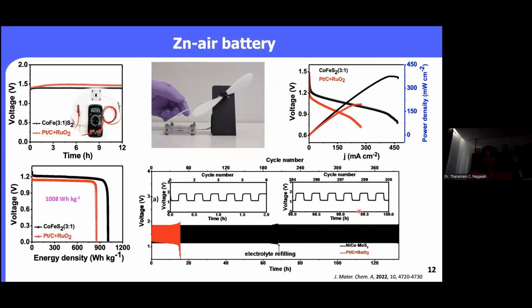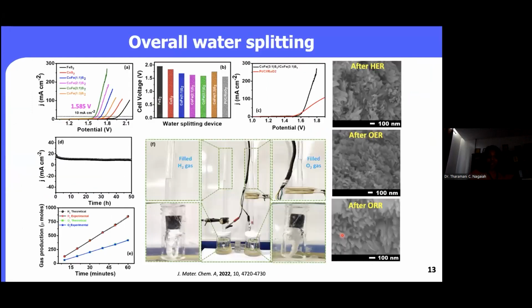And we have done the long-term stability experiments in this case. In the long-term stability test, you can see that the platinum carbon shows almost the decay in the current in less than 20 hours. Whereas in the case of our catalyst, after 70 hours, you can see that there is an increase in the potential gap. And once we refill the electrolyte, it is regained and the potential gap is maintained almost constant even up to 150 hours.